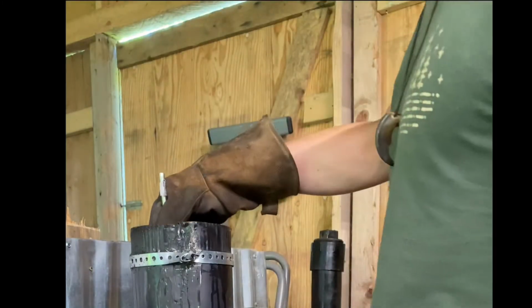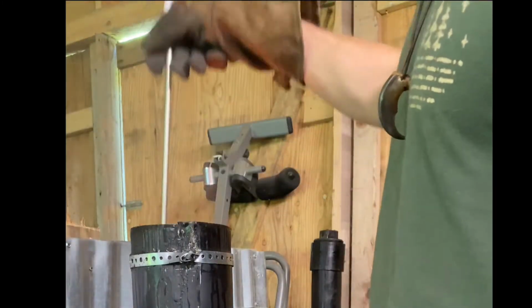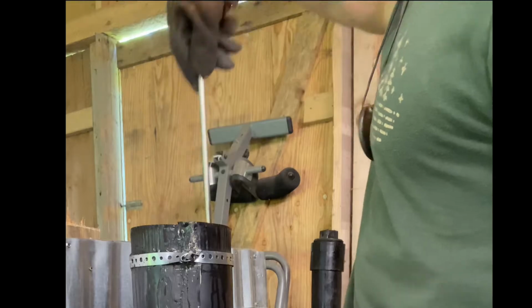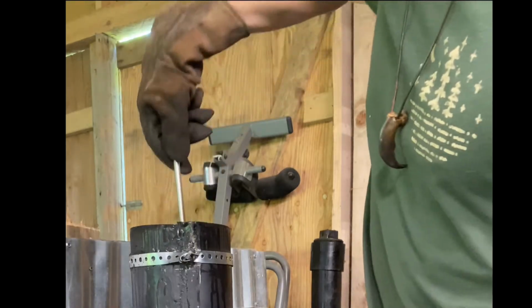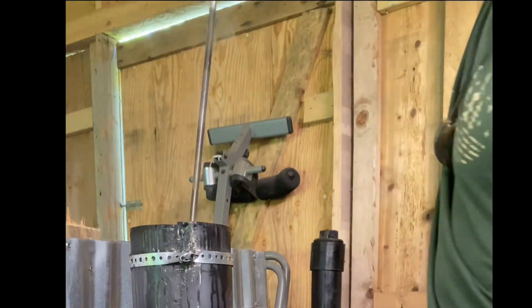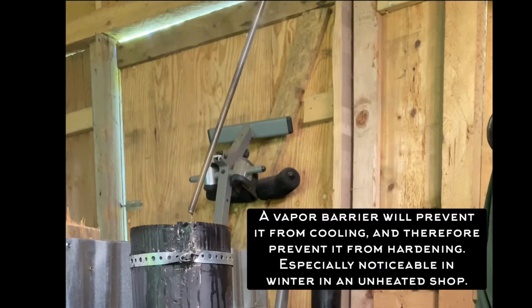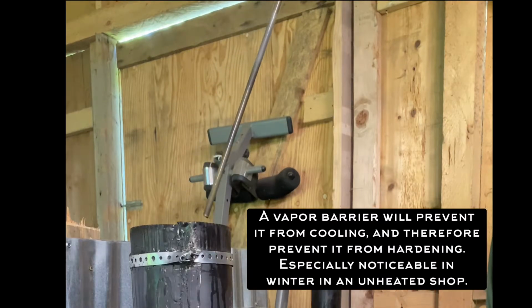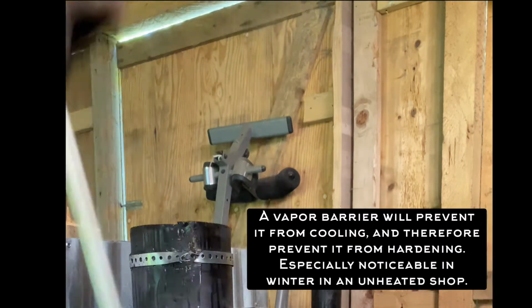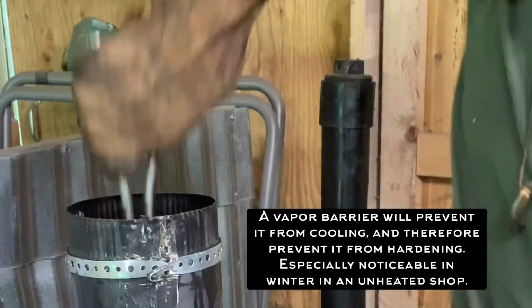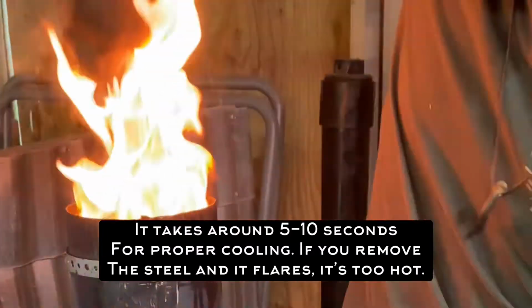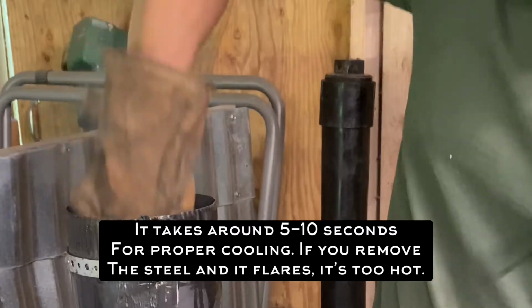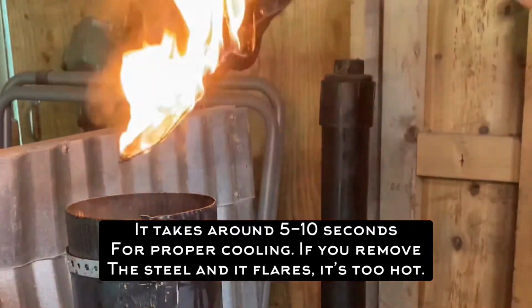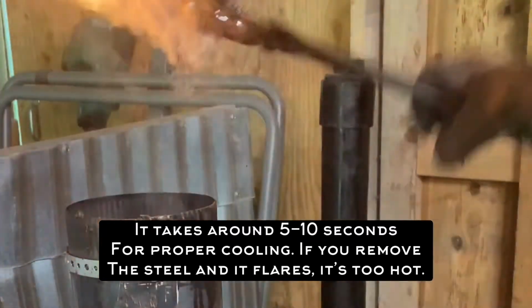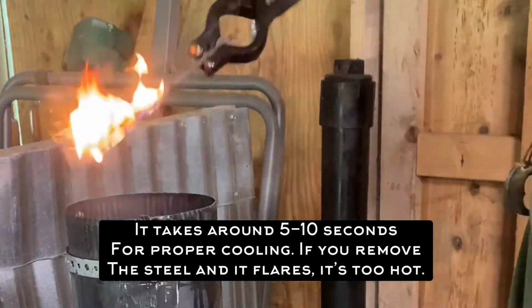Now here I'm taking some scrap metal and I'm preheating the oil to about 120 degrees Fahrenheit. The reason you do that is because if there's too drastic of a contrast between the material and the oil, you'll create a vapor barrier. Now here, as I'm quenching it, I pulled it out of the oil a little early to show you what can happen if your steel isn't cooled off enough. You'll get a fireball. Looks great on TV, but it's not great for good hardening.